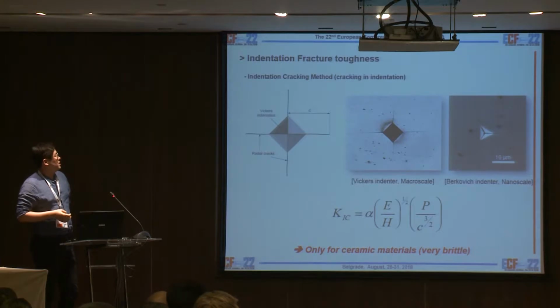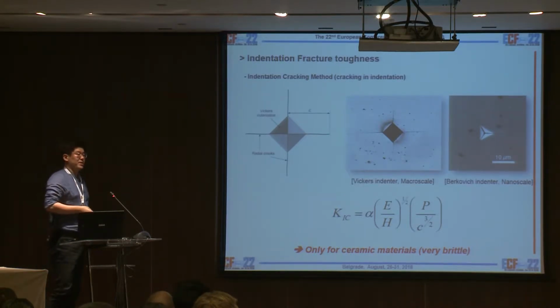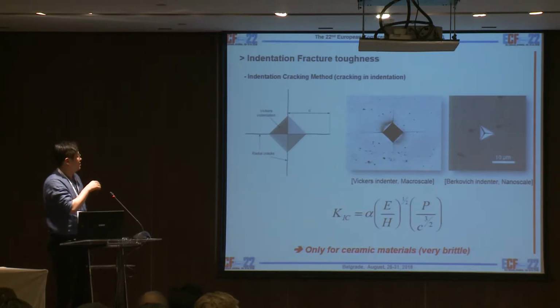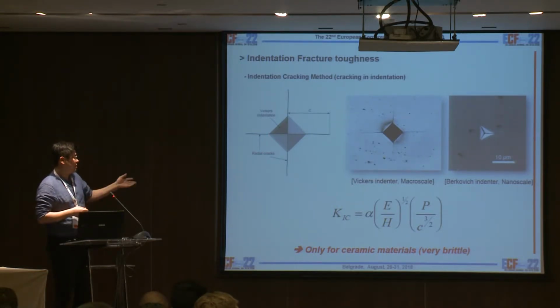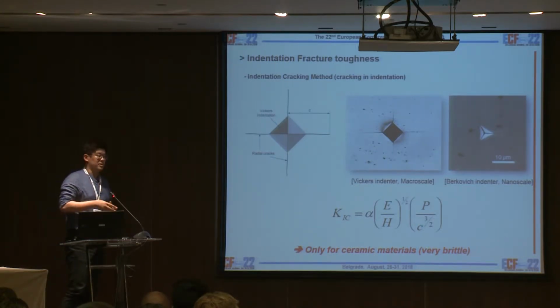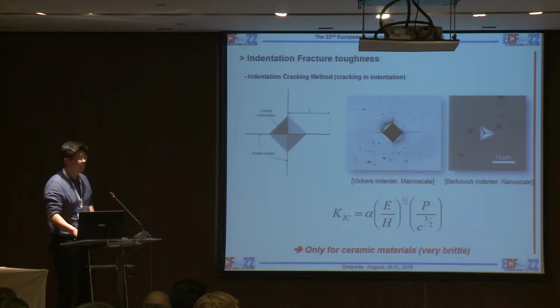Actually, there was the indentation cracking method with the Vickers indenter on glasses. With the Vickers indentation test, cracks occur in the plate, and they measure the crack length and calculate the fracture toughness. But this method is only for ceramic materials, which means very low fracture toughness values.